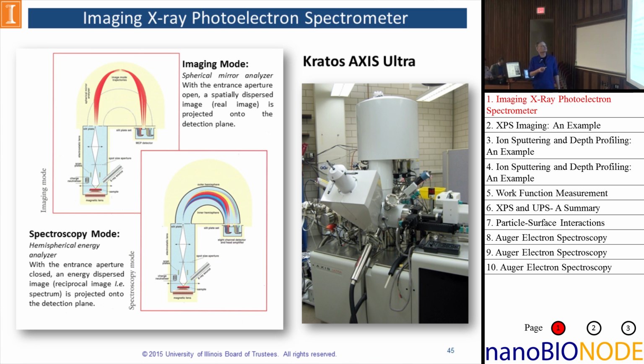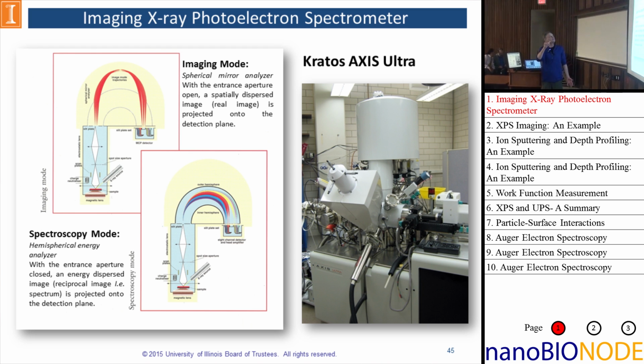you can not only do high energy resolution spectroscopy like you saw earlier this morning, you can also, by having, in this case, a hybrid analyzer, where it's basically two analyzers in one, run the instrument in different modes. So in this case, we'll open up the aperture at the entrance plane of the analyzer. And so then in this mode, we'll transfer a two-dimensional image of your sample to the detection plane. And in this design, by putting the detection planes both in the same plane, and they're both real imaging planes, you could jump back and forth between spectra and imaging quite conveniently without needing to move your sample.